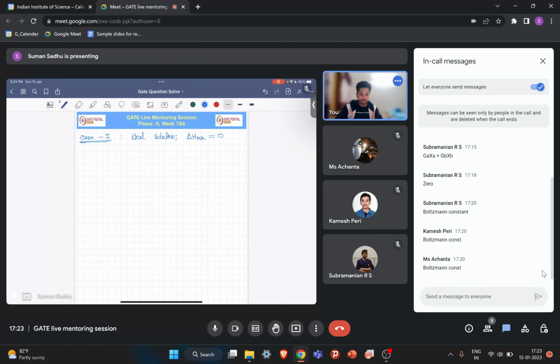If delta H mix is 0, then G of solution will simply be x_A G_A plus x_B G_B plus RT (x_A ln x_A plus x_B ln x_B), right?